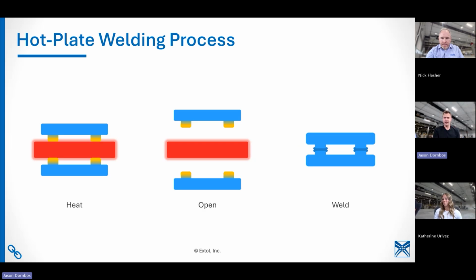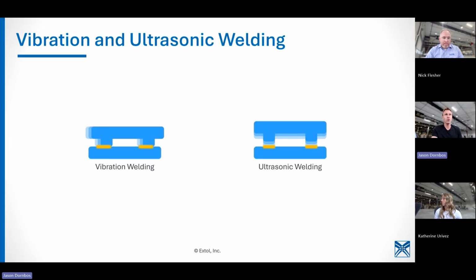Ricardo says he's got a new project for vibration welding, and it's PMMA with a high gloss black, and there's concerns that there's going to be marking on that part from the vibration process. I'm going to pull open a slide so people can follow along. When we say vibration welding, we're talking about the one on the left. That's two materials linearly being vibrated left to right. And it's a pretty aggressive process. You're applying a force and sliding back and forth to get the friction to generate heat. And because it's vibrating, if you aren't holding your plastic part really tightly, the plastic is going to shake in the nest itself, and that's going to scuff the plastic part like crazy.